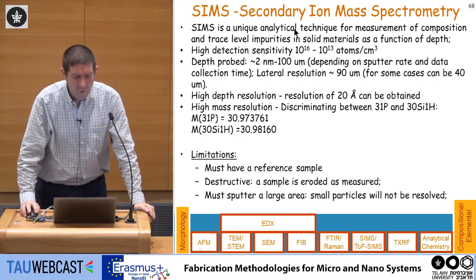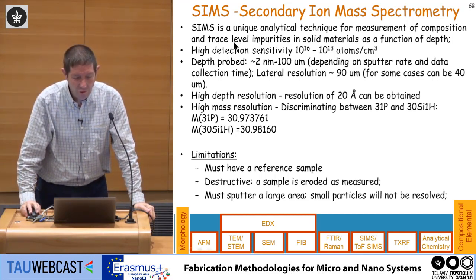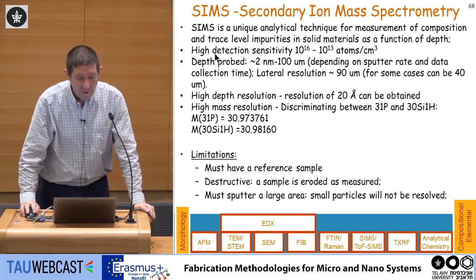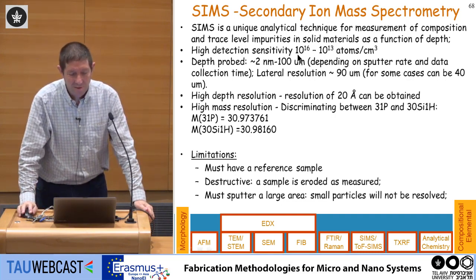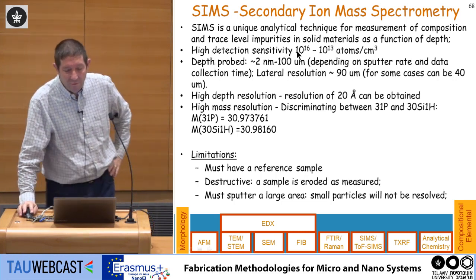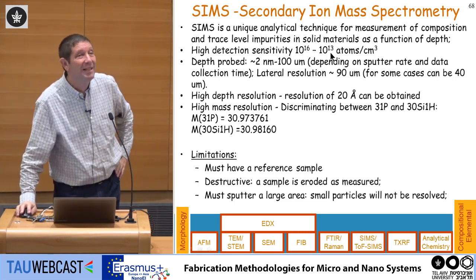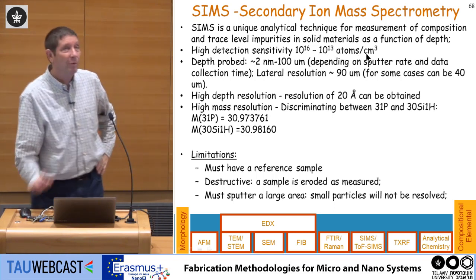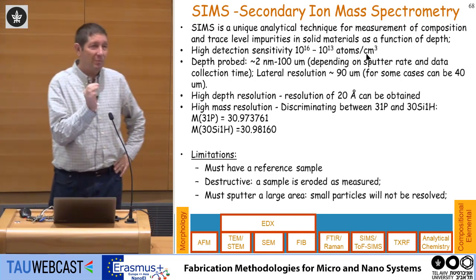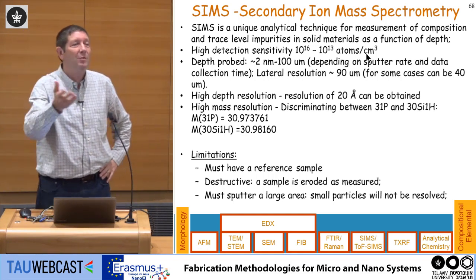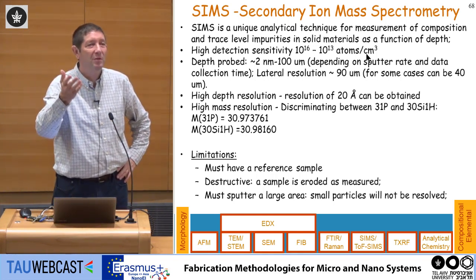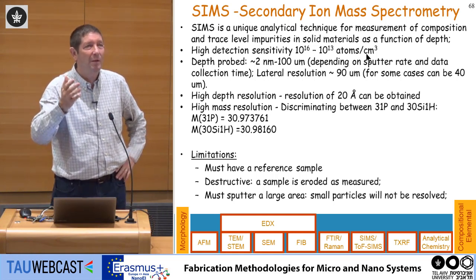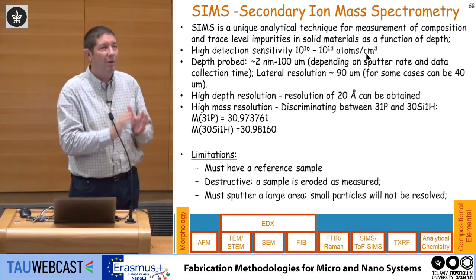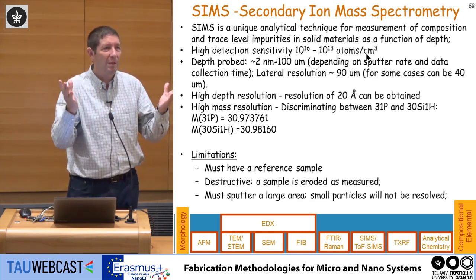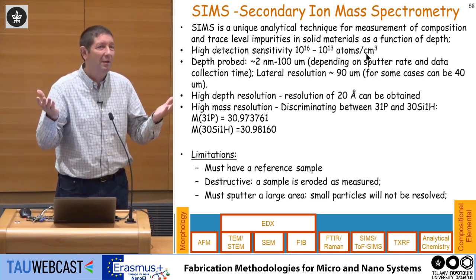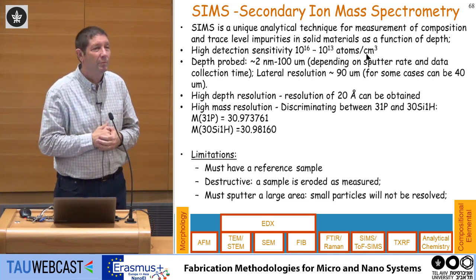It's a very unique analytical technique for measurement of composition and trace level impurities. It has extremely high detection sensitivity. You can go down to a sensitivity of 10 to the 13 to 10 to the 16 atoms per cubic centimeter. I have to remind you, I hope you remember, how many silicon atoms we have per cubic centimeter of silicon? Do you remember the number? Approximately 10 to the 22.